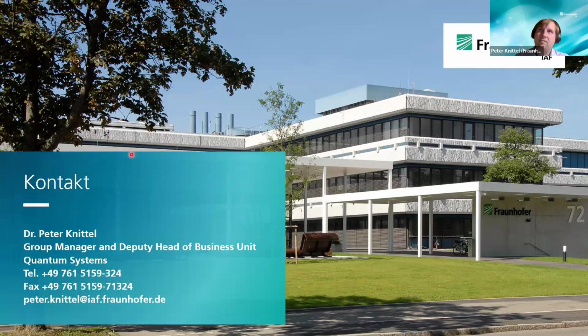Yeah, it's most probably something related to the chemical potential. We've also observed this in case of phosphorus doping. There you also see an increase in growth rate, whereas for boron doping it's the other way around. So if you add a p-type dopant, you actually decrease your growth rate. So in that case, it seems to be very much related with the chemical potential.